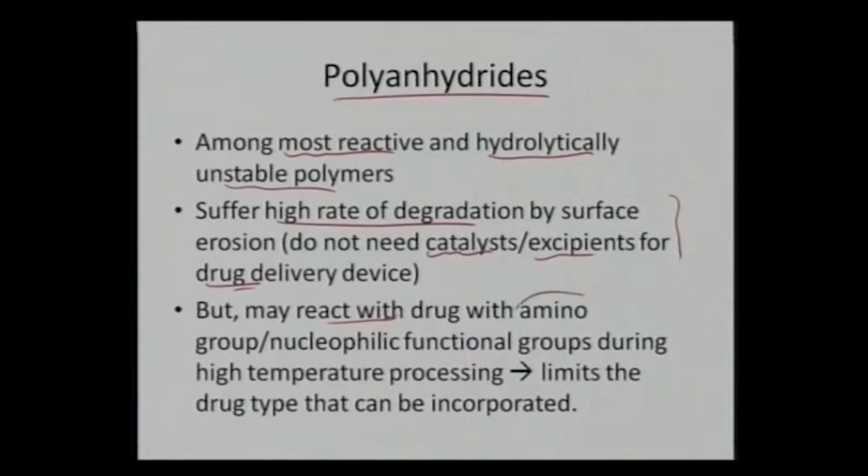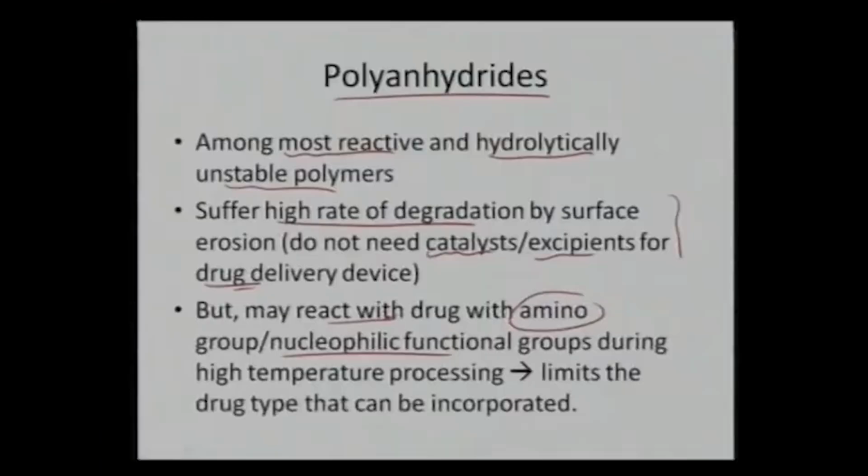So they tend to react with the amino group or nucleophilic functional group when the material is being processed. The processing has to be done to mix the drug with the polyanhydride, and it has to be done at a little higher temperature, above the melting temperature of the polyanhydride. During that process it starts to react with the amino or nucleophilic functional group, and that limits the drug which can be easily incorporated with the polyanhydrides.